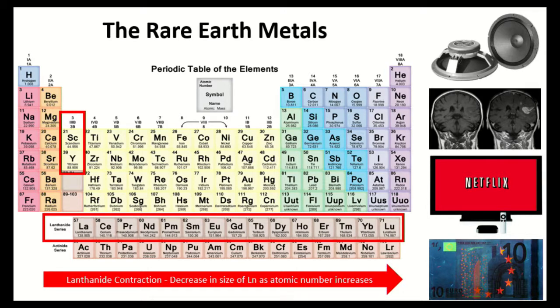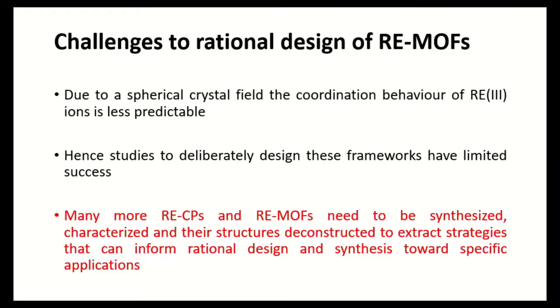So there is significant advantage to incorporating the rare earth elements as the nodes in these metal organic frameworks, but there are challenges, however. Due to a spherical crystal field, the coordination behavior of the rare earth elements is less predictable. In fact, while there are many isoreticular families of transition metal compounds, as you can see from Zayar's presentation, we were one of the first groups to form an isoreticular rare earth family of compounds. You have many transition metal reticular families, but I think currently there are only 4 of those families for the rare earth elements.